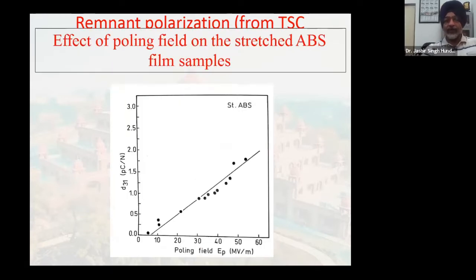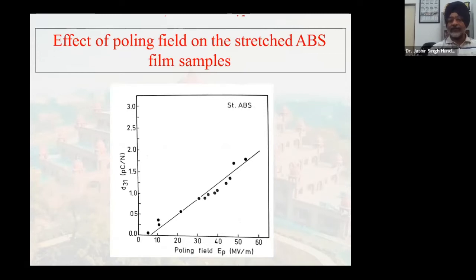Okay. So D31, this is in the case of the other polymer we were talking of, that is acrylonitrile butadiene styrene. We find that again D31 increases with the poling field. In fact, nobody else had studied ABS earlier. Okay, so we were the first people to study it, and we were able to get up to 2 picocoulomb per Newton. So the results were not very promising, so we didn't do much higher studies in that, but yes, we did study this cyanopolymer as well, where D31 was studied.